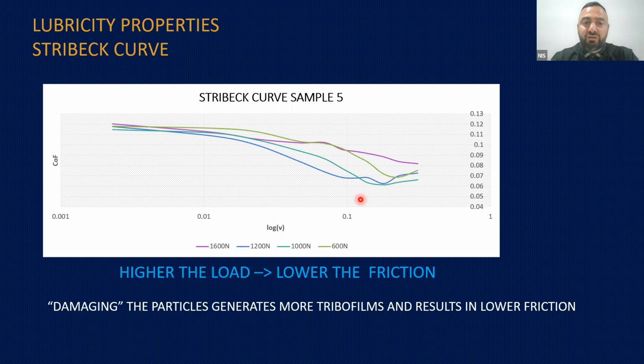But what this test really shows here: we took sample 5, which has 0.27% of particles, and we ran the Stribeck curve at different loads. At 600 Newtons, friction was quite high across. The higher the load, we went to 1000 Newtons to 1200 Newtons, the friction started dropping. And that's a very important point. In a regular lubricant, usually it's the other way around. The more load you apply to the system, the higher friction you start getting. But here, because the solid particles are not soluble, they're solid in the system, you start damaging the particles more. And the more you damage them, the more tribofilm you generate. The more tribofilm you generate, the more your friction drops.